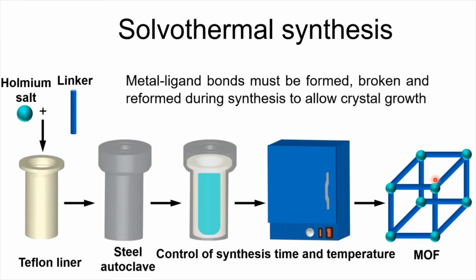Now, how are these made? Well, the most common method for growing these MOFs is solvothermally, which just means you have your holmium salt precursor and your linker precursor, and you dissolve them in a common solvent, and once you heat them up, these metal ligand coordination bonds will start forming and breaking until it actually stabilizes to your desired product, and it will come out of solution, and that's how you obtain your MOF.